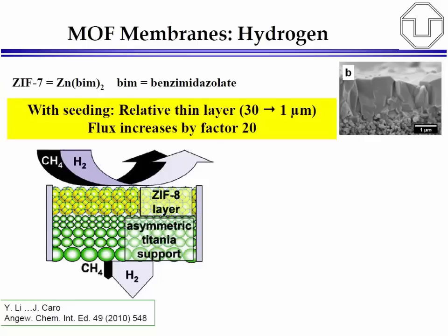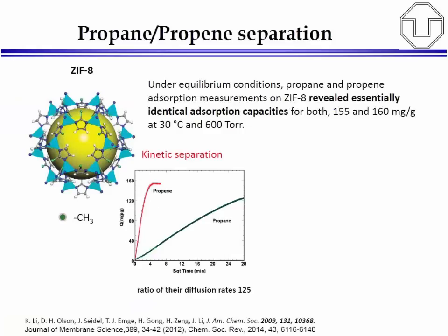And this could be interesting for these more simple gases like hydrogen separation, but people are looking now also into, and this shows the next slide, into, for example, propene separation. That's on the next slide. And here also ZIF-8 has quite a good selectivity, this time not because of the thermodynamics of adsorption, but due to the kinetic separation, because the propene is somewhat a more lean molecule which can easily and quickly enter the pore system, while the propane is a bit more lazy, and in this way a kinetic separation is achieved.